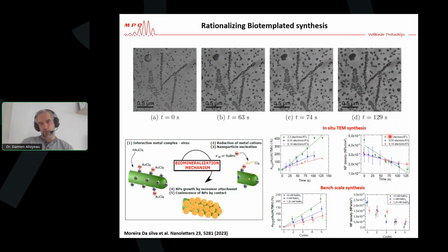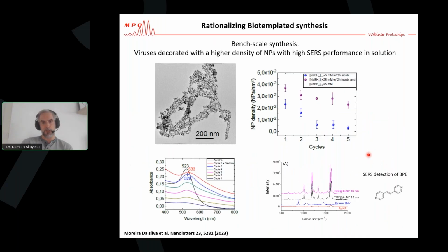Now, what is more interesting to see is the effect of the dose rate on the nanoparticle density. And you see that when you have a very high dose rate for the first cycles, you have a strong nucleation burst. But then, if you want to avoid the decrease of the nanoparticle density, you have to have a growth of the nanoparticles that is extremely slow to avoid the coalescence. So from this in situ experiment, we have been able to see that if you want to increase the density of nanoparticles on the surface of the virus, you need to have a first cycle of reduction with a very high concentration of reducing agent, and then use additional reducing cycles with a very low concentration of reducing agent.